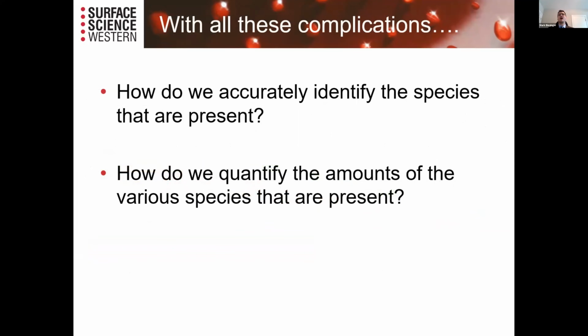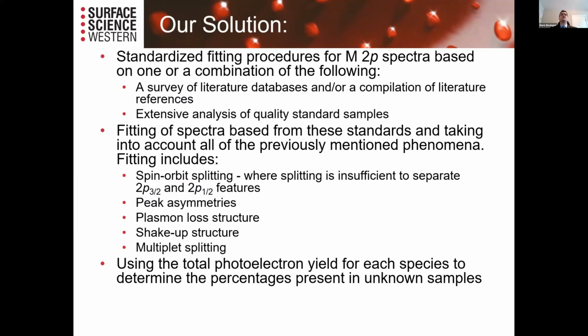So with all these complications, how do we identify the species that are present, and how do we quantify the species that are present? And so that's what a lot of this work has been done to do. Our solution has been to first do a survey of literature databases and a compilation of literature references to see what's out there, and then do an extensive analysis of quality standard samples. And so then we take the fitting of those spectra from those standard samples and take into account all the previously mentioned phenomena, including spin orbit splitting, peak asymmetries, loss structure, shakeup structure, multiplet splitting, and then use the total photoelectron yield for each species. So all the structure that's attributed to each species is used to determine the percentages of those species present in unknown samples.